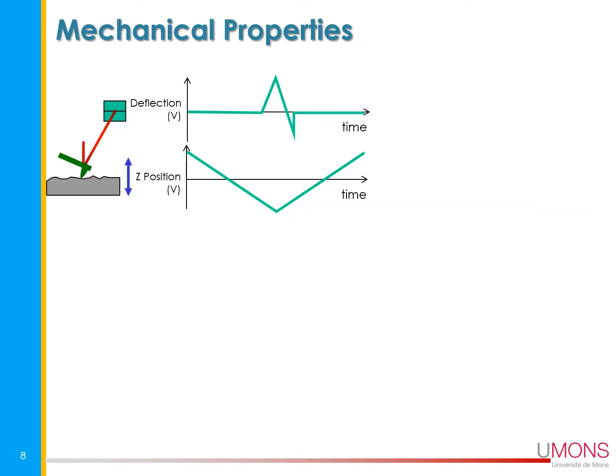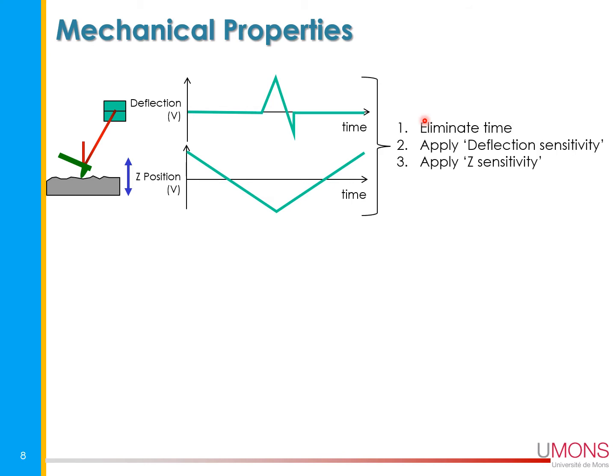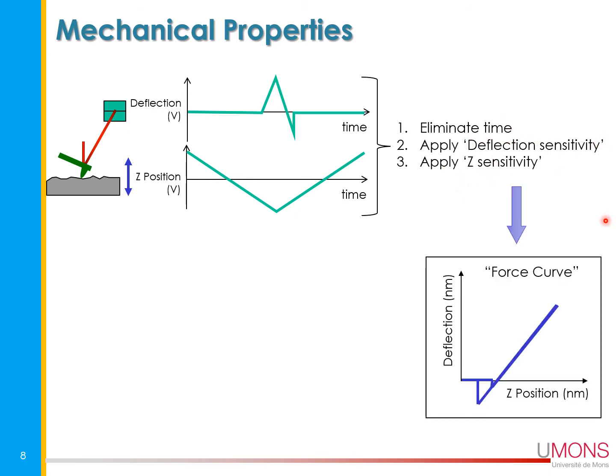So for the mechanical properties, as we saw before, we are measuring the deflection versus time, and we are recording the force distance curve. And this is the movement of the piezo going from up to down and then coming out of the surface. When you are recording those curves for each pixel of the image, and then by eliminating the time, of course, if you pre-calibrate your system, you know the deflection sensitivity, the Z sensitivity, it's possible to derive and to get this force curve, the deflection versus the position.